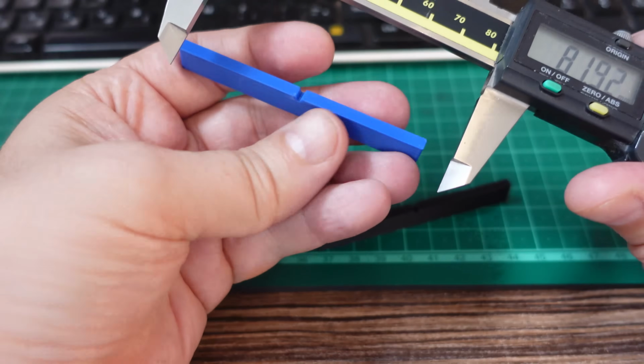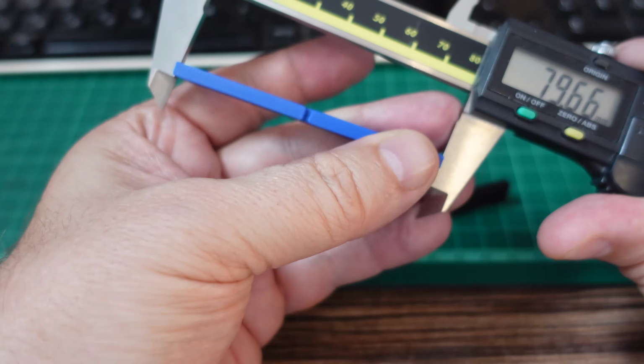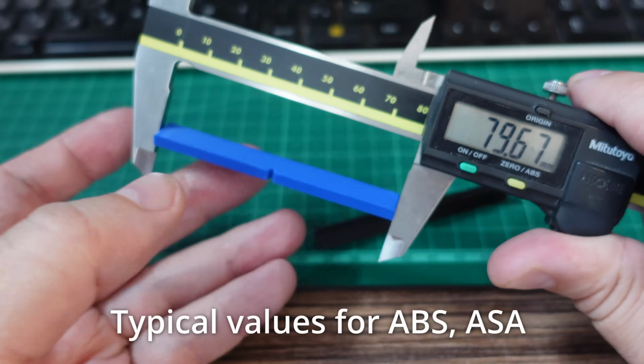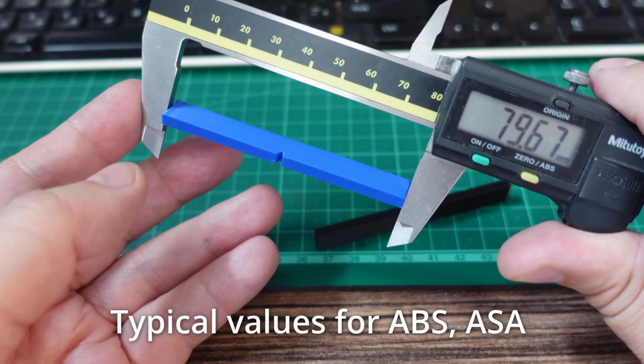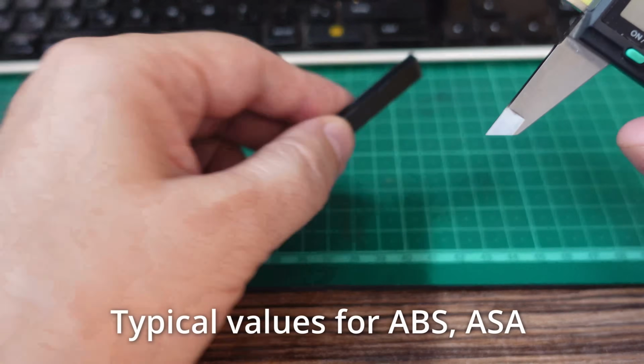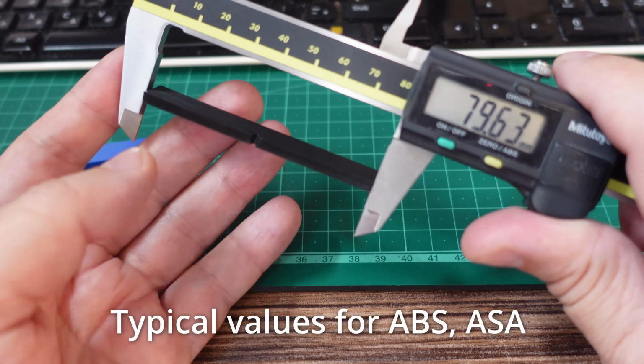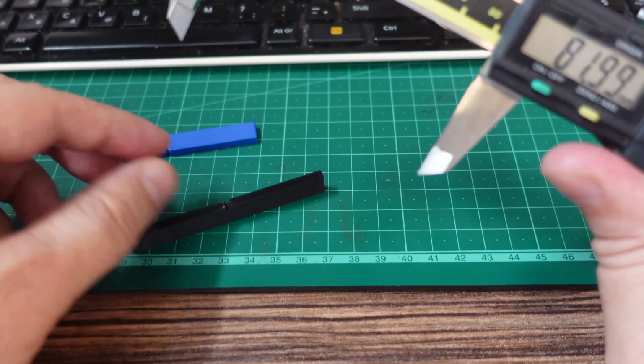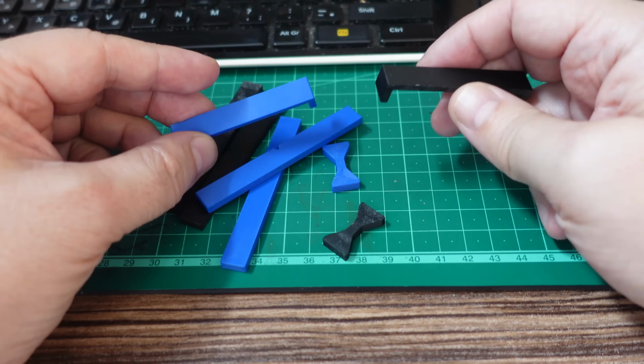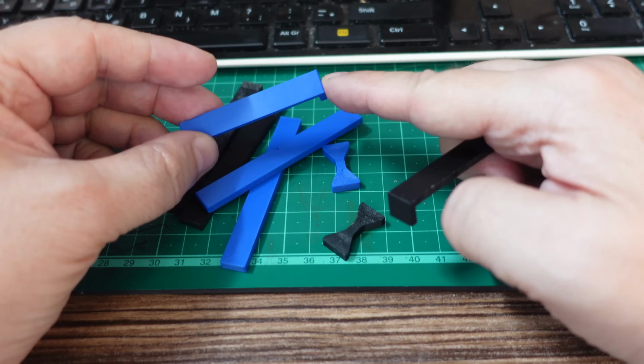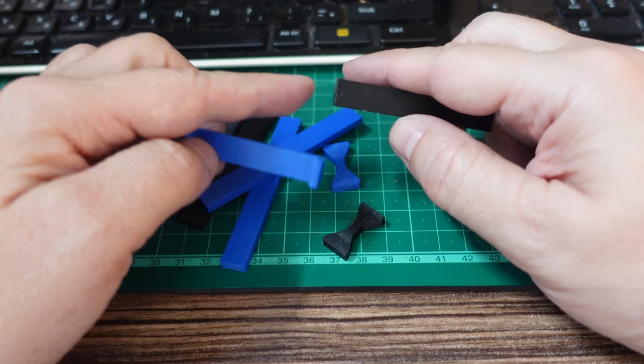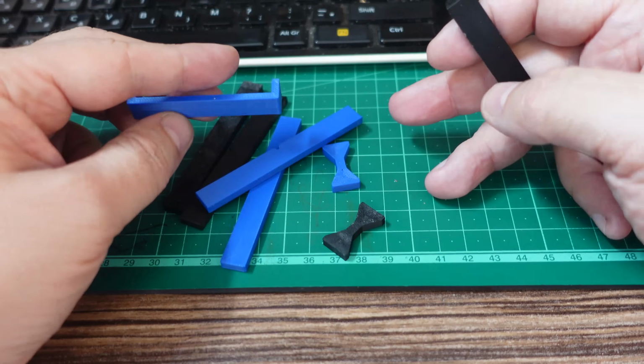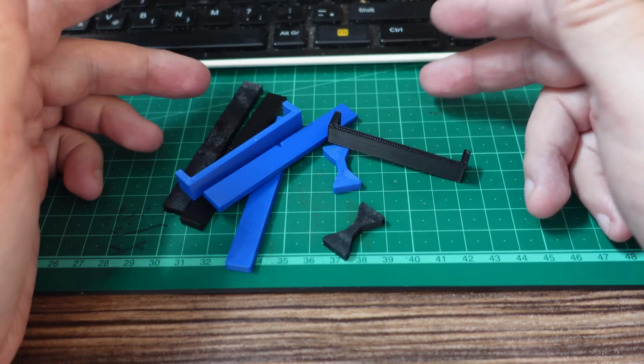Just quickly, I want to measure the shrinking. This should be 80 millimeters. And I'm measuring about the elephant foot, 79.67. 79.63. Interesting. I measured several parts, and yes, a little bit less shrinking on the ASA part compared to the black ABS part. And theoretically, this should reduce the warping, and also we will have better dimensional accuracy.